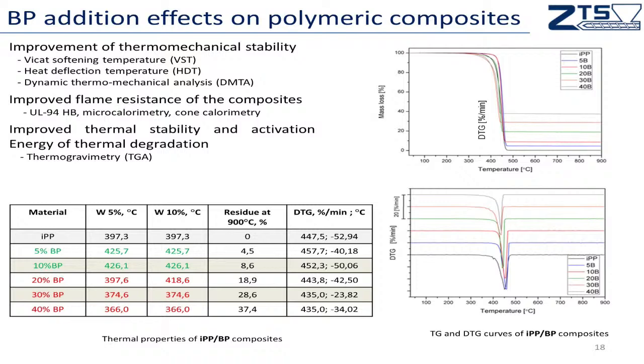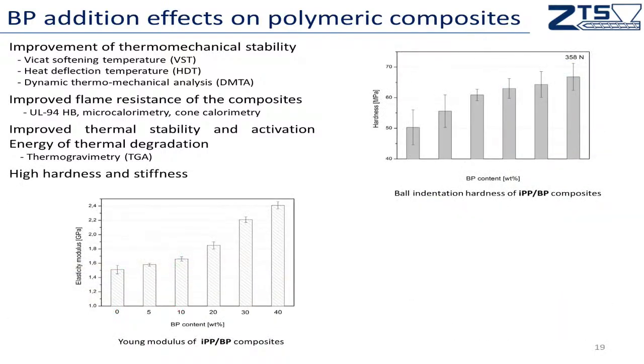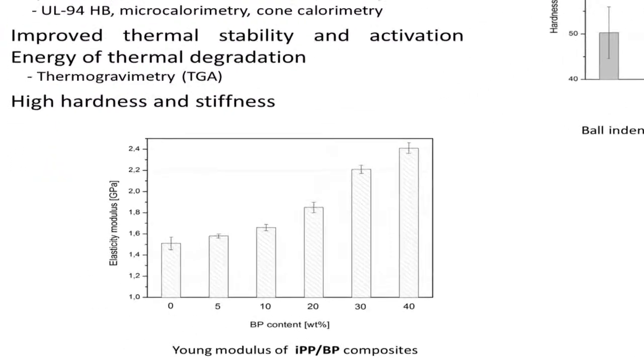And if we move to another slide, we can see that, as can be expected, the hardness of the material, in this case I present the example of the isotactic polypropylene, was increased, as well as the Young modulus, so the stiffness of the material is significantly increased. And those two phenomena were observed for all of those materials, for polyurethane, for the epoxy resin, PLA. In each case, the hardness and stiffness of the material were improved.